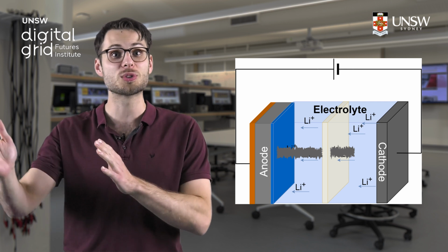Well, internal short circuits may occur in a lithium-ion battery due to manufacturing defects, mechanical abuse like a compressive shock, or a phenomenon known as dendrite growth. In this phenomenon, dendrites are tiny needle-like projections of metal that can grow inside a lithium-ion battery cell from an electrode through the electrolyte and can eventually cross from one electrode over to the other, causing a short circuit. Dendrites are often formed by operating a lithium-ion battery under abnormal conditions like overcharging or low temperature charging.